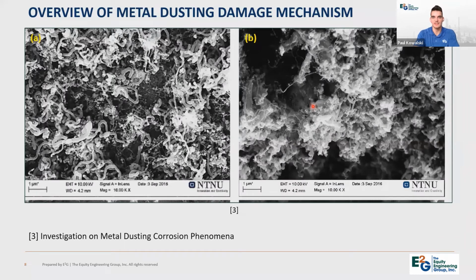And this is just an SEM image, scanning electron microscope image of the surface of a material that has undergone metal dusting. And the white filaments and, for lack of a better word, blobs are really the carbide formation and the graphite formation from the metal dusting having occurred. So again, just another visual to help understand this mechanism.